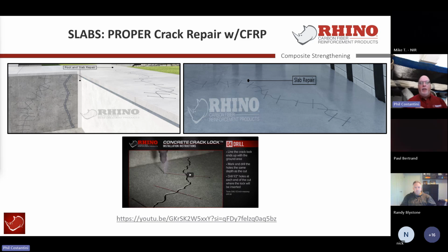Typically in years past, I would utilize epoxy rebar, especially in a food environment or an industrial environment that's got a lot of moving traffic with steel wheels and forklifts or any type of pallet jacking equipment. Those slabs usually take a pretty good beating. And if they start cracking, like loading docks, for example, or, a classic example in our community, parking garages, it's usually the exit ramps that get a lot of hellacious cracking, sometimes due to salt, sometimes due to chlorides, sometimes just because the slab was under designed for vehicular traffic.